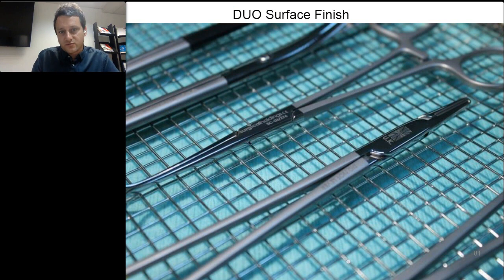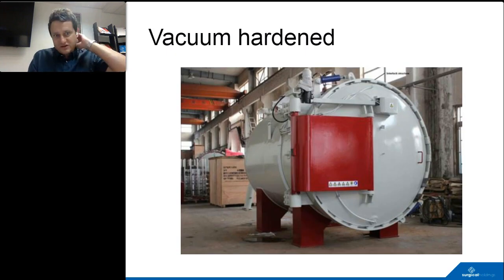This is a duo finish with a bright polish and what we call a wet bead blast finish on the other side. And to mention vacuum hardening, as I showed at the very start, obviously we have our forgings and they're soft. We do all those different processes at some stage or another on the instrument, and then once it's all finished, you would have polished it up to a significant level. The instruments will go off to be vacuum hardened at another vendor who have these big vacuum hardening machines. The instruments are vacuum hardened and tempered to a really, really tight tolerance. They come back and obviously they're hard and functional for what they need to be.